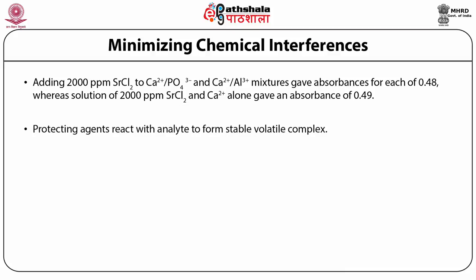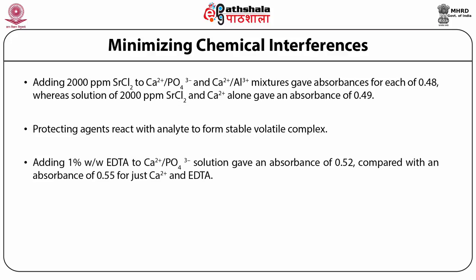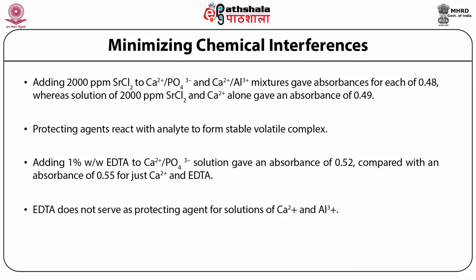Protecting agents react with the analyte to form a stable volatile complex. Adding 1% weight by weight EDTA to the calcium phosphate solution discussed in the preceding paragraph gave an absorbance of 0.52 compared with an absorbance of 0.55 for just the calcium ion and EDTA. On the other hand, EDTA does not serve as a protecting agent for solutions of calcium and aluminium ions.